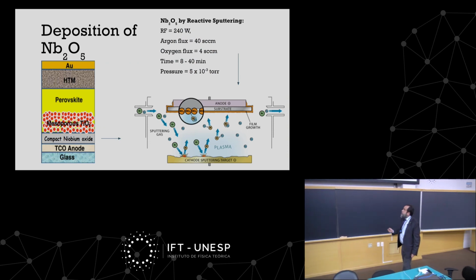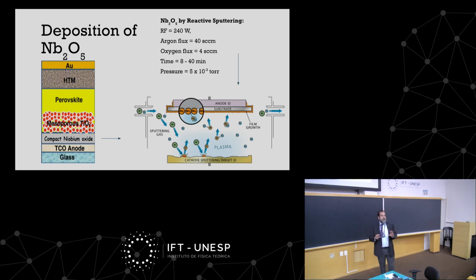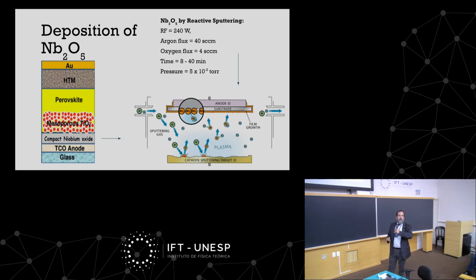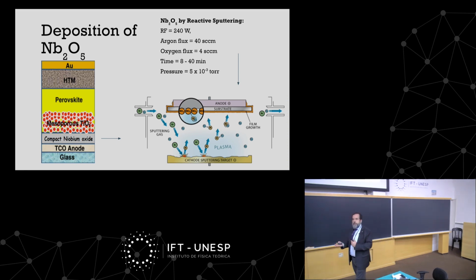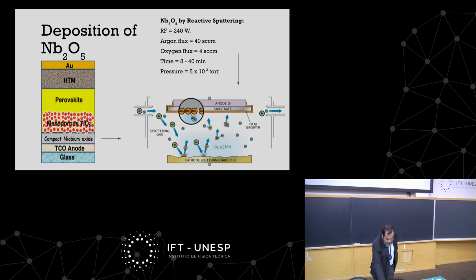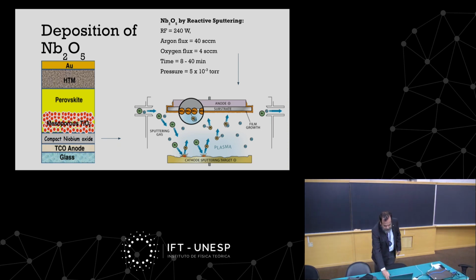The sputtering technique, for those who are not used to, is a technique for depositing thin films. And there are some nice and bad things about it. One of the nice things is that you can control the reaction very well, because basically the technique uses argon to bombard a niobium target in this case. And the niobium is ejected. And if I have oxygen inside this vacuum chamber, there is a reaction and you produce this oxide. And you can control by the flux of oxygen and argon how much oxygen, for example, there is inside the film. Okay? So it's a very nice technique to produce very homogeneous films in the lab or in the industry.